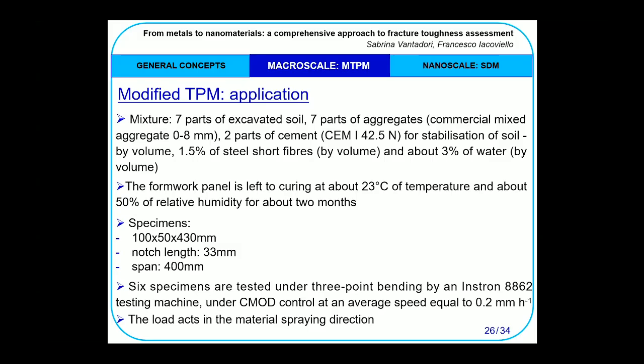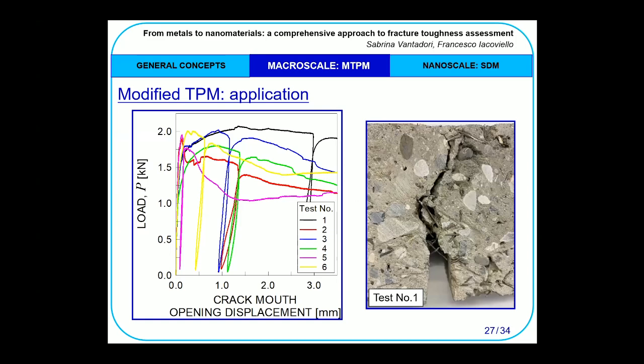6 specimens are tested under 3-point bending by using an instrumented testing machine under crack mouth opening displacement control, employing a clip gauge at an average speed equal to 0.2 mm/hour. The load acts in the material's spraying direction. In this slide, the load versus crack mouth opening displacement experimental curves are reported and used to measure the initial compliance Ci, the unloading compliance Cu, and the peak load Pmax.